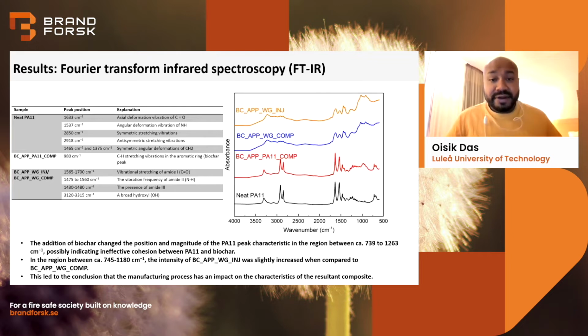So we also did an infrared spectroscopy analysis of the different samples. For polyamide-based samples, we see that in the characteristic peak region of 739 to 1200 centimeter inverse wave number, there has been a change in the peak, which can indicate that there's an ineffective cohesion between the polymer and the biochar doped with APP. And in the region from 745 to 1180 centimeter inverse, the intensity of the injection molded sample was a little more compared to the compression molded sample where the plastic was molten. So we can conclude that the processing has an effect on the formation of the composite, and this has caused two samples, in fact, the compression molded polyamide 11 and injection molded gluten, which had APP doped biochar, to not be formed.